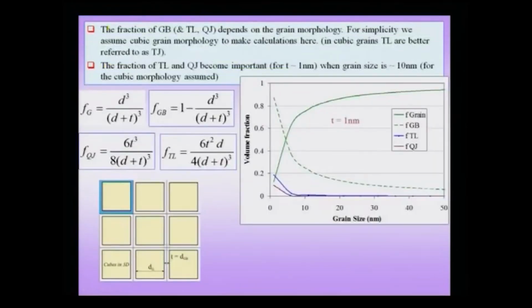The fraction of grain boundaries, and of course triple lines and quadruple junctions, depends on the grain morphology. For simplicity, we have assumed a cube morphology to make our calculations very simple, and in cube grains triple lines can also be referred to as triple junctions, as often done in literature. The fraction of triple lines and quadruple junctions become important when the thickness is about 1 nanometer and the grain size is of the order of 10 nanometers or below, which we shall see very soon from the plots and the way we make the calculation.